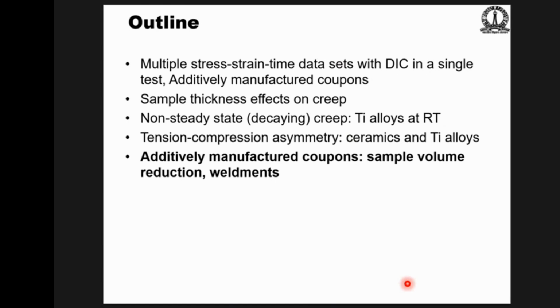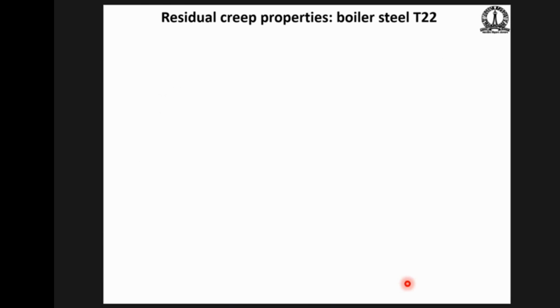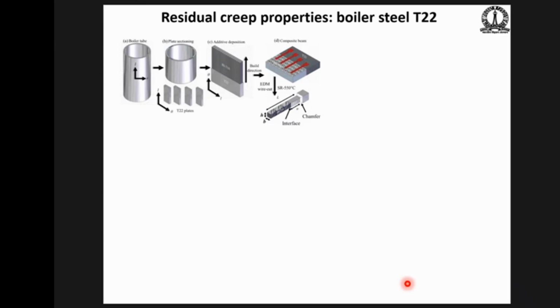Let me come to welds and additive manufacturing. One of the programs we undertook was to look at the residual creep behavior of boiler tubes. These had been run in steam turbines for up to 27 years. And the question was whether this technique could be used to take very small coupons out and see whether the creep properties had deteriorated. Because depending on what the creep properties were, you could decide to continue the boiler for another 5 years, which is not insignificant, even after 27 years, or whether the tubes had to be changed.